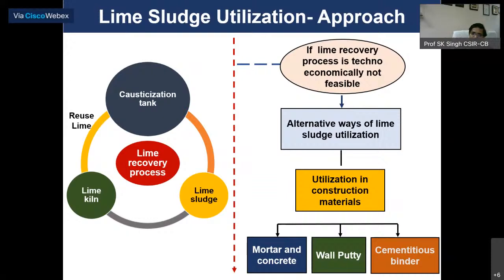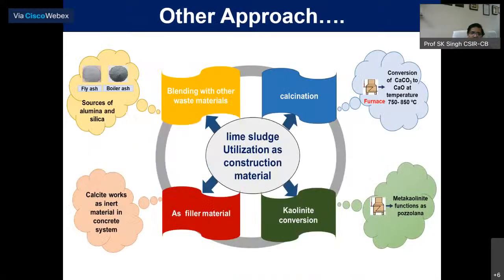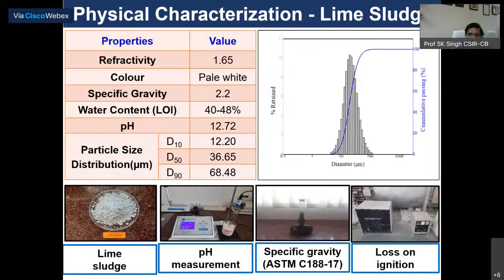We have processed this lime sludge to make good mortar, concrete, wall putty, and cementitious binder. It may be a composite cement, a belite cement, or gypsum and other things. So that was our approach. We have also looked at it as a fine aggregate and performance enhancer in ordinary Portland cement, because the code allows it to be added up to 5%. I will show that its particle size is very small, so it can be used as a performance enhancer.